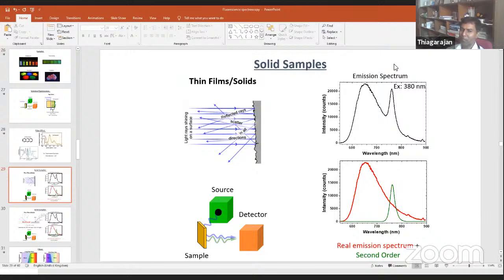Most of the time, emission from the nanomaterials we cannot say quantitatively. If you record the same solution at two different times, you can get two different emission densities, or the wavelength may shift, because the particle scattering may be different from solution to solution, and the number of particles, and whether the particles are uniformly solubilized. A lot of factors are involved, so it's very difficult to quantify it. From my own experience, I never use it for quantification, but I can use it as qualitative. For a qualitative purpose, we can use it, no problem. For a quantitative purpose, I'm not sure about it.